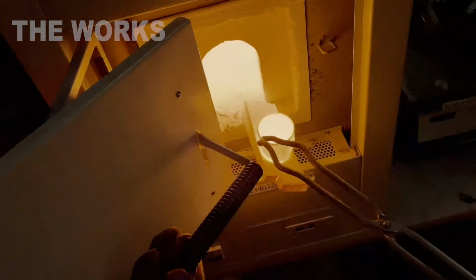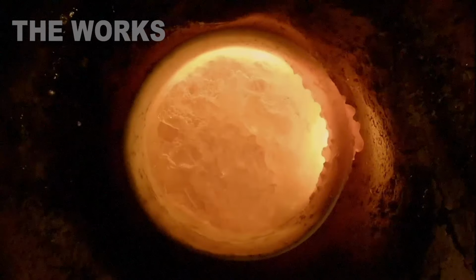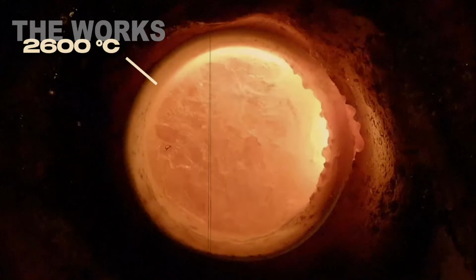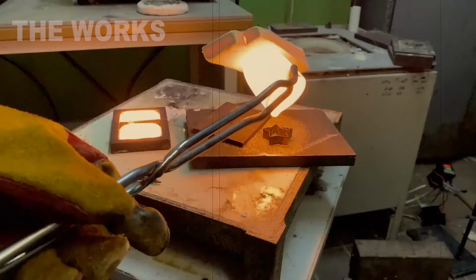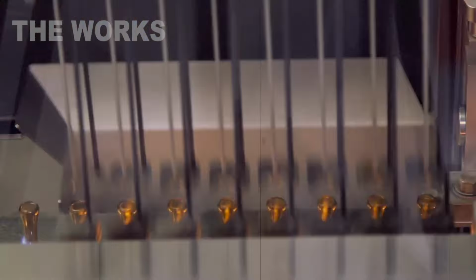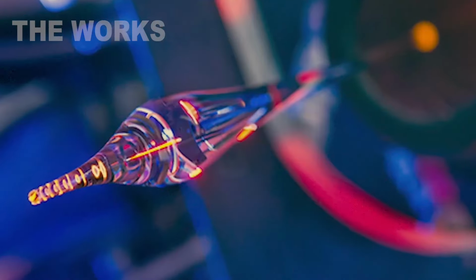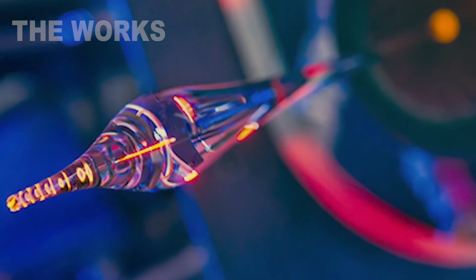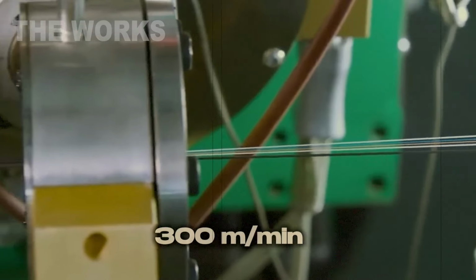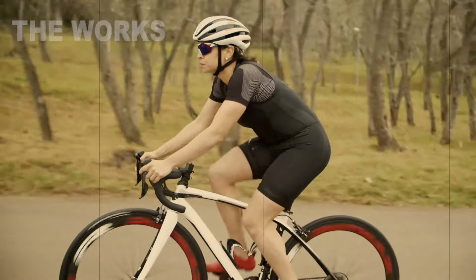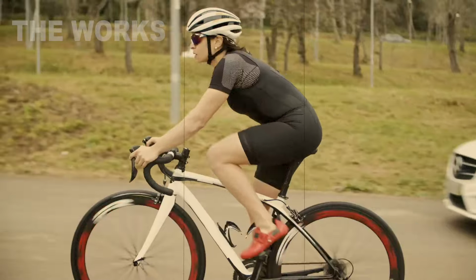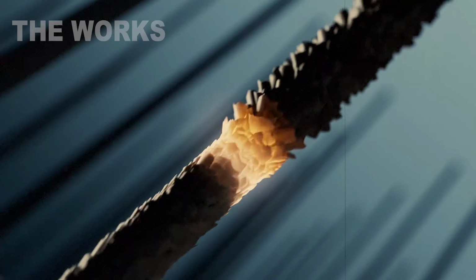The preform is placed in a special furnace where the temperature reaches approximately 2,600 degrees Celsius. This temperature is so high that the glass becomes soft and begins to melt, like caramel on a hob. When the preform's end melts, a drop of molten glass begins to drip from it. This drop is very carefully drawn downwards, and from it forms the finest thread. This thread, the optical fiber, is drawn at speeds of roughly 300 meters per minute. Imagine, that's faster than a cyclist moving through the city.